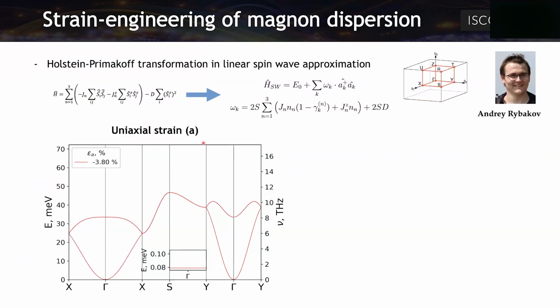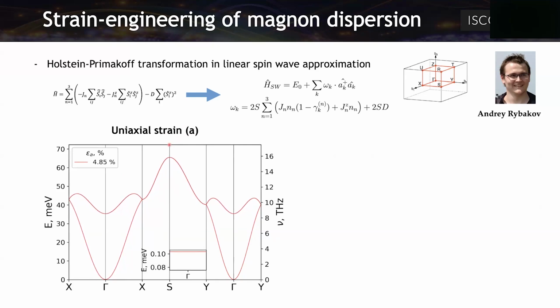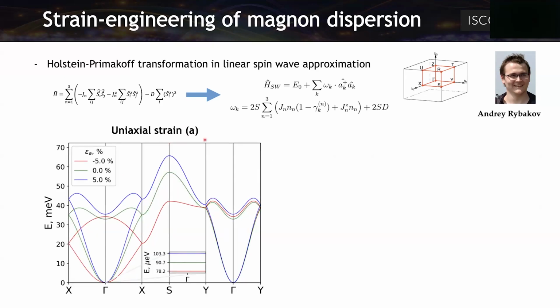And then we can calculate the magnon dispersion with this exchange interaction we have calculated, performing the Holstein-Primakoff transformation. In this case, we are now seeing how the magnon dispersion evolves when we are expanding the material. So as I said before, uniaxial strain along A is increasing the exchange interaction. And we can see here the final picture.